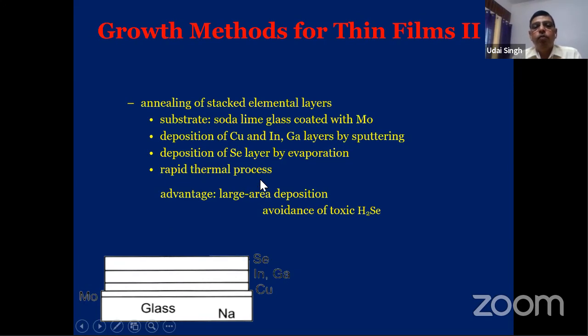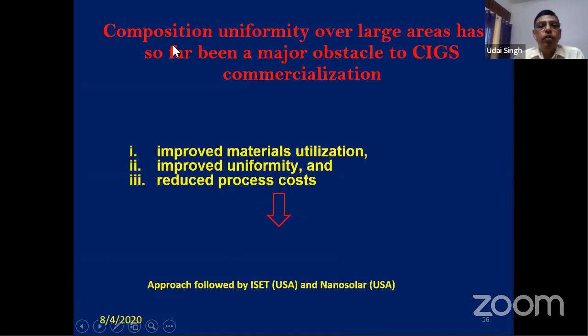So these 2 methods are more familiar. But if you see this non-vacuum process, people have thought, because you can control the composition very well, improved material utilization. In sputtering, if you are using a sputtering target, only 40% is used, 60% is lost. But if you have a manufacturing unit, you can have a contract with the supplier, where you can give the target again and then you can buy back. But if you are lab scale, it's all disadvantage, because only 40% is used, 60% is waste.